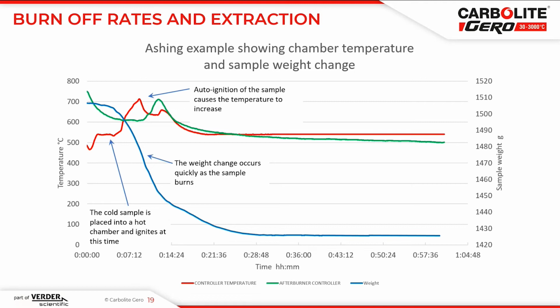minutes. Then it's followed by a rapid increase in temperature above the set point. So remember our set point's 540, and you see the red line rising up to 700 degrees C in this case. So that's caused by the sample material igniting, and as it burns, it's increasing the temperature in the chamber. The blue line shows the weight of the sample, and during that burning phase, we see the weight reducing. As the sample weight reduces to a constant value, we also see the temperature returning to the set point of